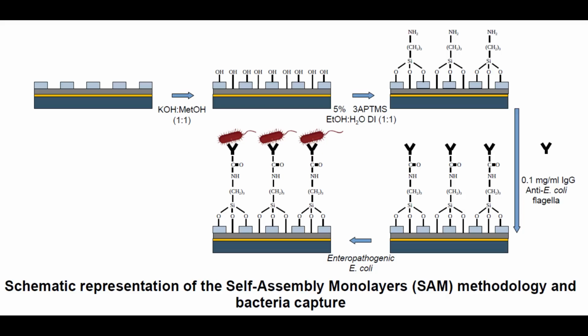To obtain the biosensor, the transducer underwent a self-assembled monolayers methodology. This involves forming OH groups on the silicon carbide surface using potassium hydroxide, followed by exposing the device to 3-aminopropyltrimethoxysilane to generate amine groups. Specific E. coli antibodies are then adsorbed onto the surface. To characterize the biosensor's detection limit, different E. coli concentrations ranging from 1 CFU per milliliter to 10^8 CFU per milliliter were used.